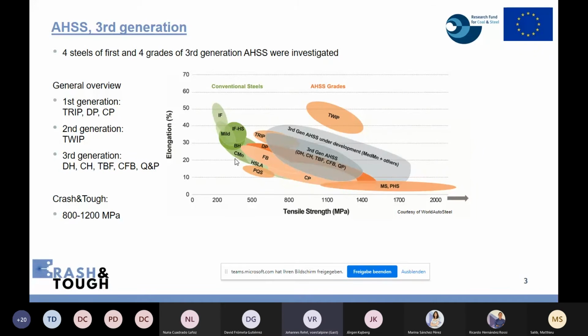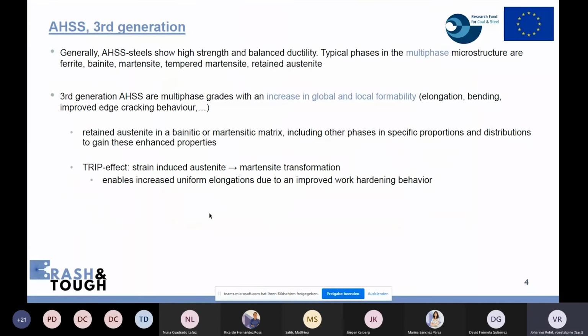the first and second generation, we have the third generation AHSS, where we have the dual phase high ductility grades, the complex phase high ductility grades, the TBF grades, the CFB, and the quench and partitioning grades. And in the Crash&Tough project, we investigated grades with strength from 800 megapascal to 1200 megapascal. Generally, we can say that the AHSS steels of the first generation show quite high strength and a balanced ductility. Typical phases in this multi-phase microstructure are soft phases like ferrite, bainite, but also harder phases, that means martensite, tempered martensite, and some retained austenite.